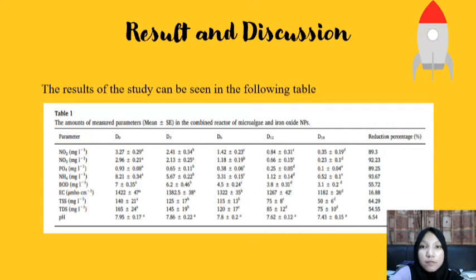The result of the study can be seen in the following table. Based on the table, the chemical test parameters measured include the content of NO2, NO3, PO4, NH4, BOD or biological oxygen demand, EC or electrical conductivity, TSS or total suspended solids, TDS or total dissolved solids, and pH, measured from day 1 until day 18. Based on the table, the trend of the results obtained up to day 18 is decreasing, and the highest percentage of reduction is the NH4 component, which is 93.67 percent. Based on the result obtained, NH4 has the highest percentage reduction compared to the other parameters.